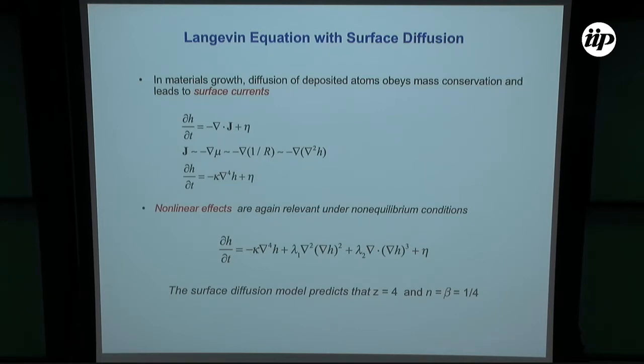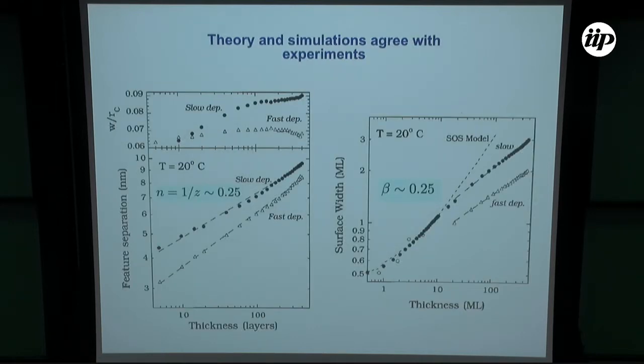But what about the main phenomenon, which is angle selection? There is no microscopic or any kind of theory for that. So what we did was we looked at the simulations, and we see the same kind of behavior in the angle, that eventually the angle does saturate. I can explain this, but it's not important. But this region shows that actually you do have faceting, as you saw in the picture, and the exponents beta and n do agree with the value of about a quarter.